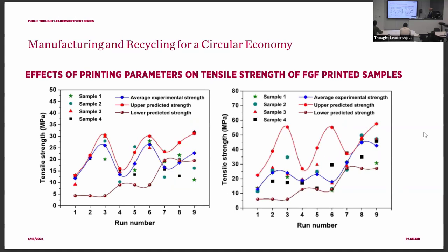And we compared those results with numerical modeling. Here you can see in the middle, the blue line is from the experimental work. And we obtained other results from numerical modeling. We made the upper and lower bounds for this analysis, and they cover the experimental work. So that means the numerical work can be used further to predict the material properties and performance.